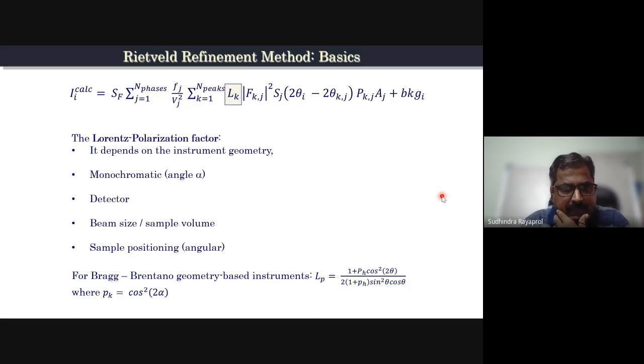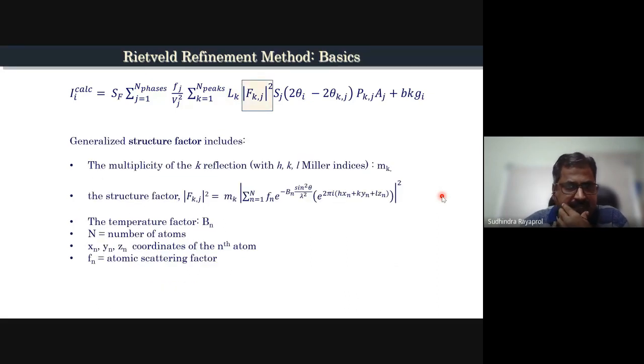Okay, it can be because of the transmission geometry or the reflectance geometry. It can be Bragg-Brentano or Debye-Scherrer method. So depending on the instrumental function, there will be a polarization factor which is inbuilt in the PCR file. There is something called the structure factor, which we have already seen. It is a combination of our atomic positions, cell parameters, the thermal parameters, and so many other factors which we have already provided in the PCR file.